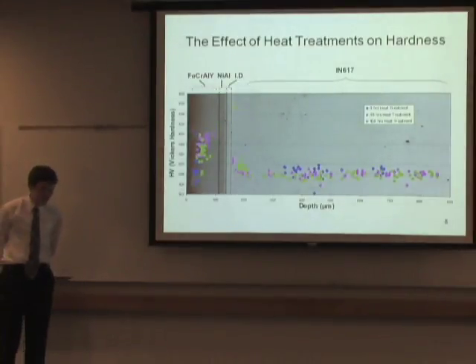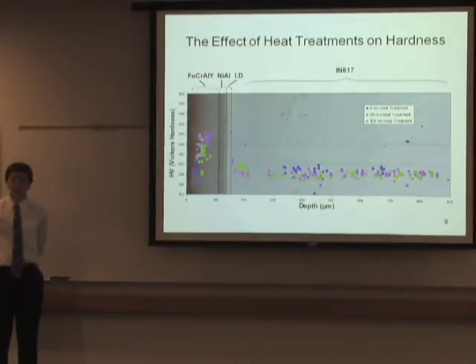So what I did when I had all of my hardness measurements is I plotted the hardness of each indent against the depth into the sample of where the resulting indents are. And it gave us a pretty good idea of what the hardness was for each individual layer. And what this graph shows us is that the FeCrAlY layer indents are a lot stronger than that of Inconel. And we were a little confused because we thought the opposite would occur.